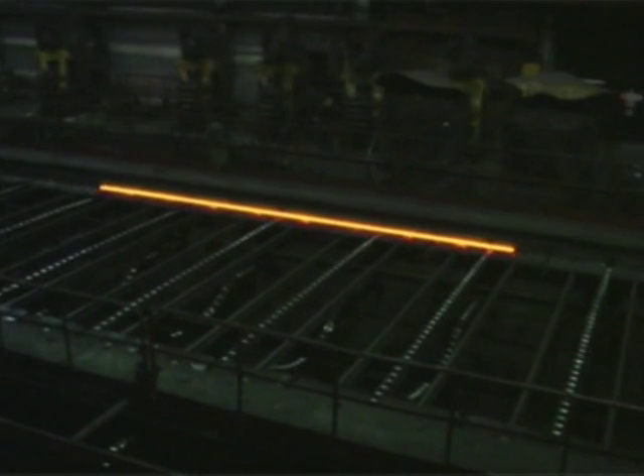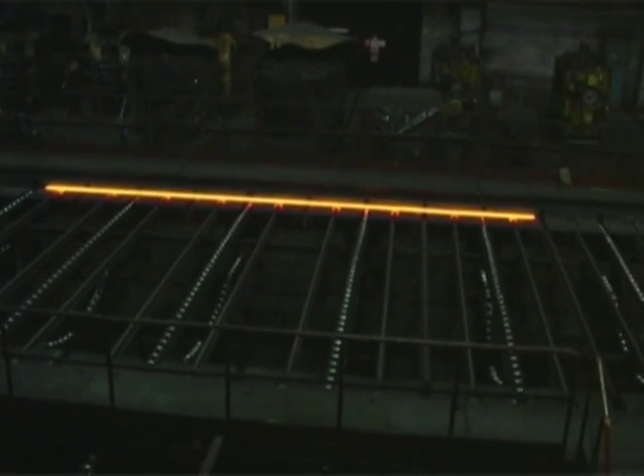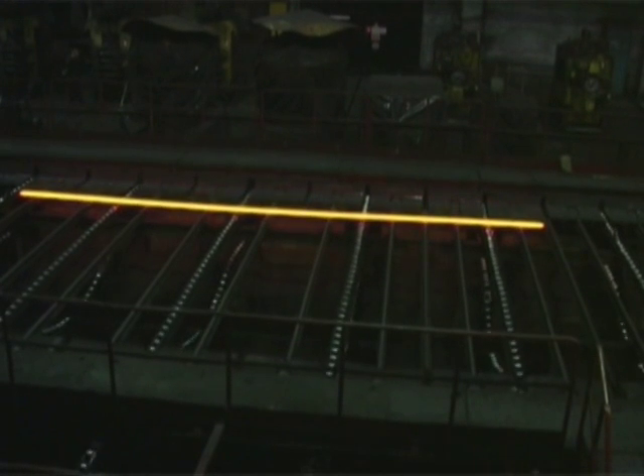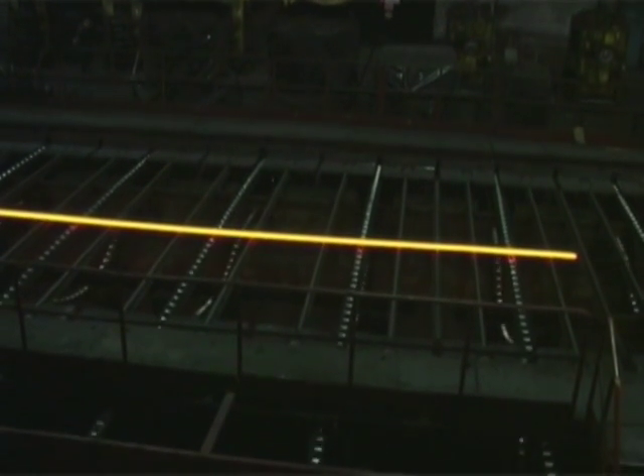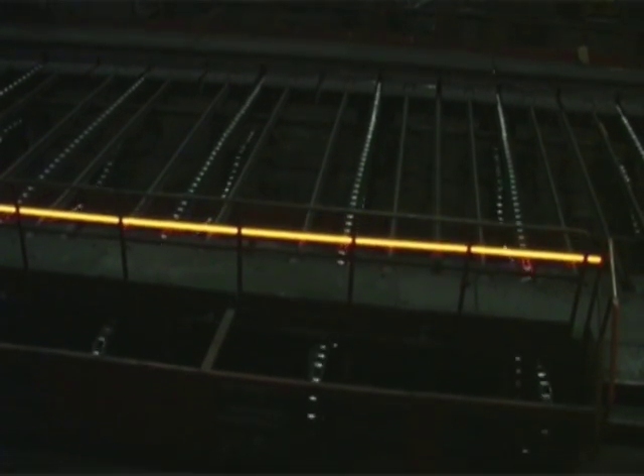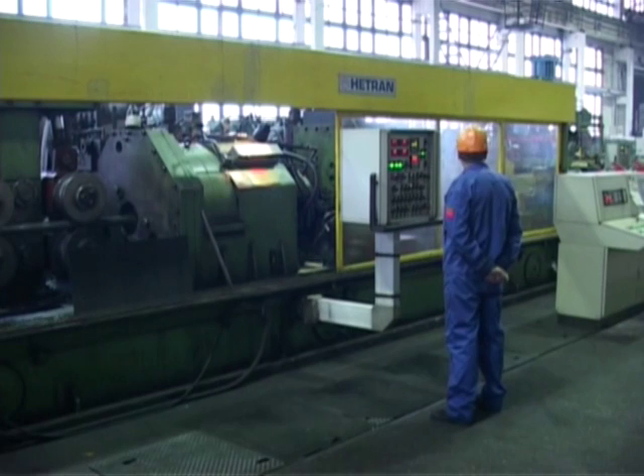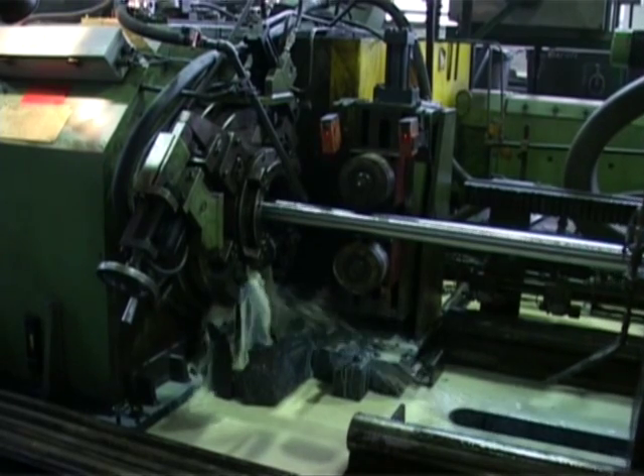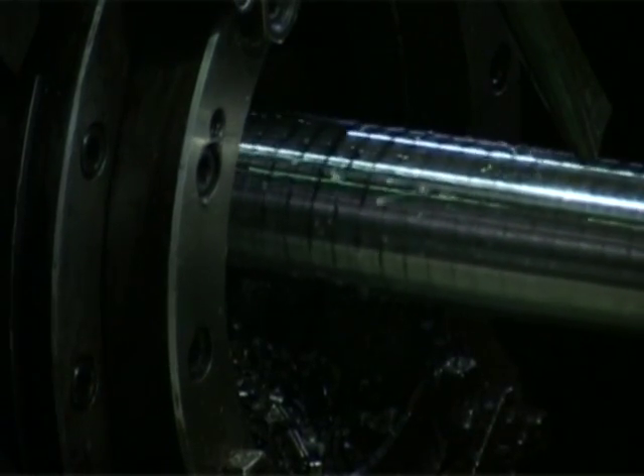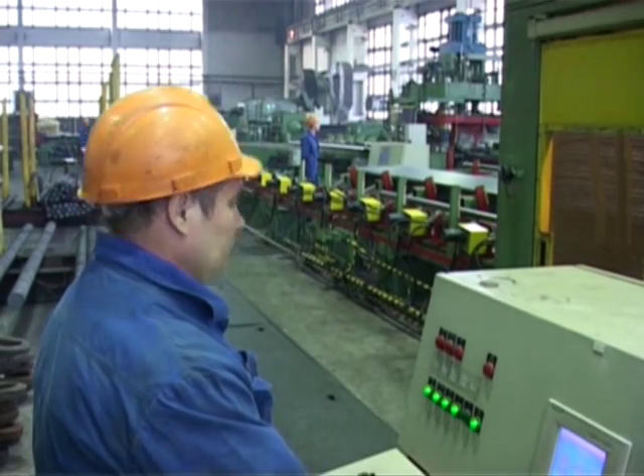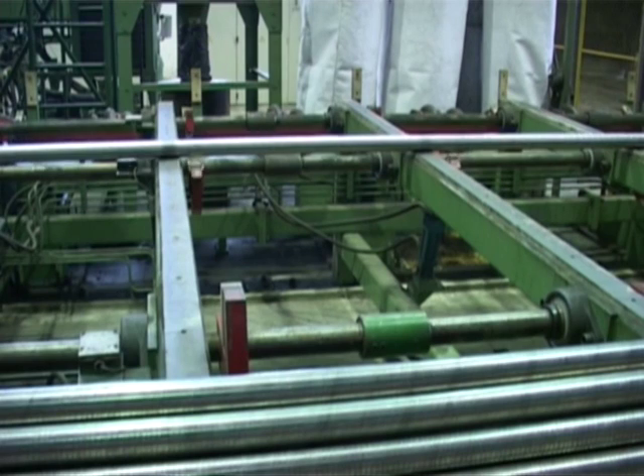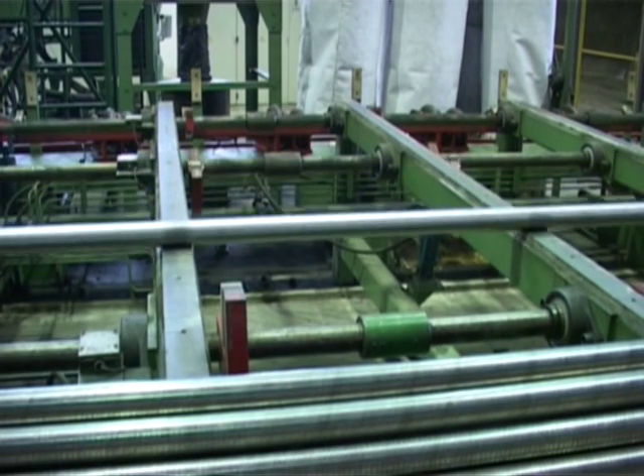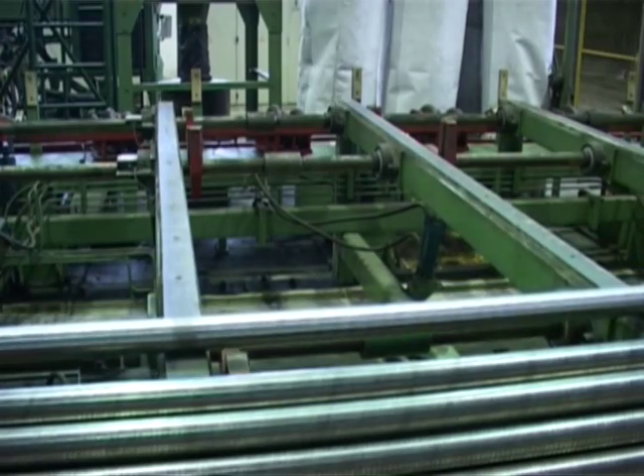The 350–250 mill is destined for production of rounds with a diameter of 8–75 mm, squares with the side of 8–45 mm, and flats equal size to them, as well as coils of wire rod with a diameter of 8-14 mm. For the purpose of increase in quality of finished metal and diversification of products, an automated surface finishing line was set into operation at the plant. The new line enables producing rolled metal with a diameter from 38 to 200 mm with the accuracy degree of H9, H11 and surface roughness up to 5 micron.